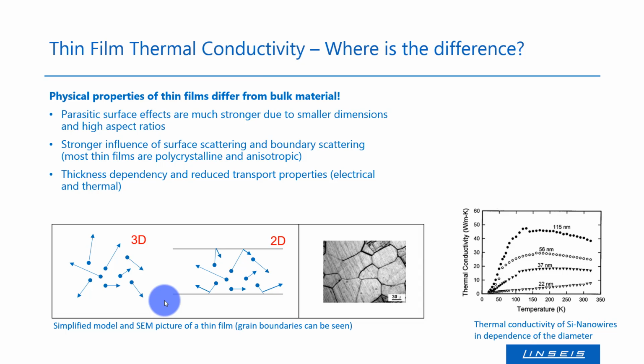It shows the thermal conductivity of silicon nanowires as a function of the diameter. We can see a clear reduction of the thermal conductivity with reduced diameter.